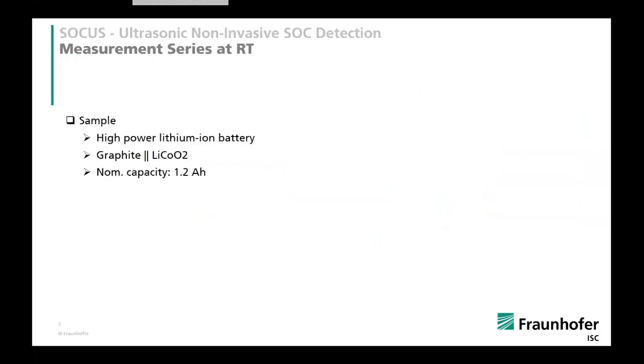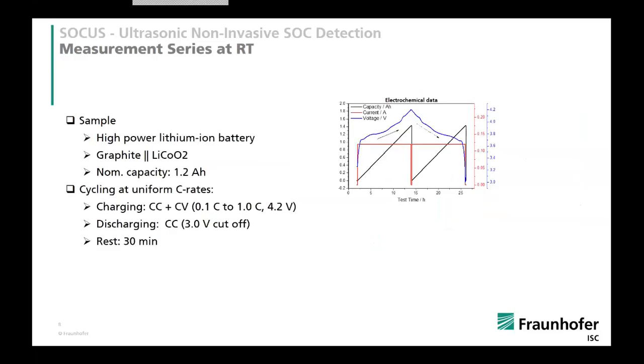So for a test, we used the battery cell I mentioned before, graphite versus lithium cobalt oxide, 1.2 amp hours, and we cycle it with quite standard procedures, CCCV between 0.1 C to 1 C to a charging end voltage of 4.2 volt, and for the discharging, just the usual constant current to a cutoff voltage of 3.0 volts. Between 2 cycles, we had a rest step of 30 minutes.